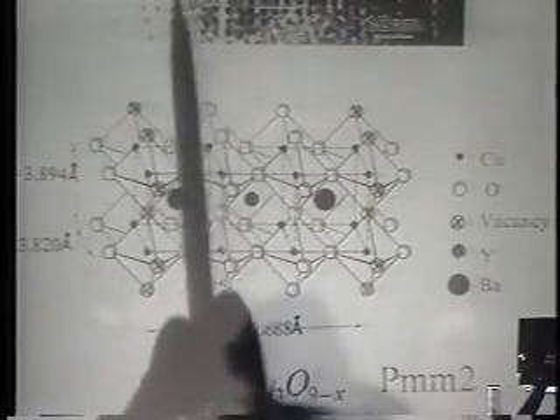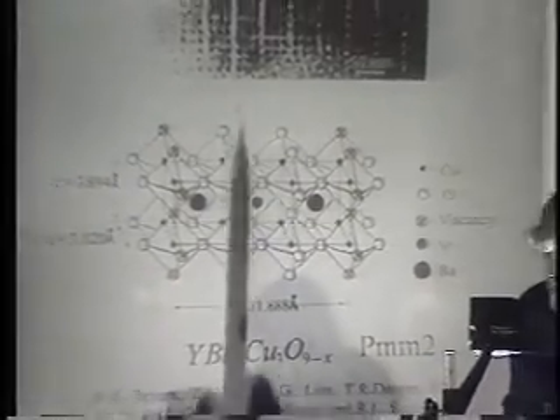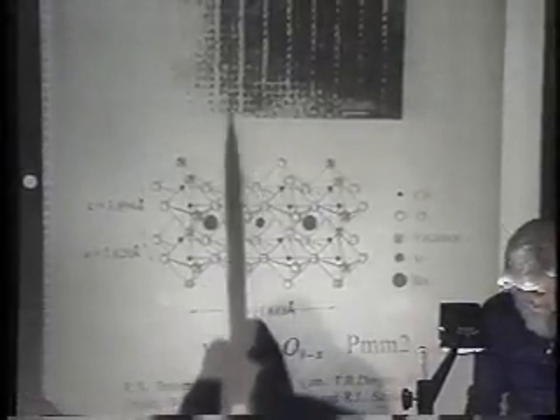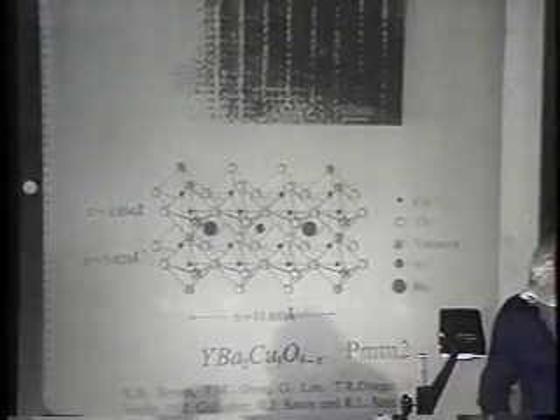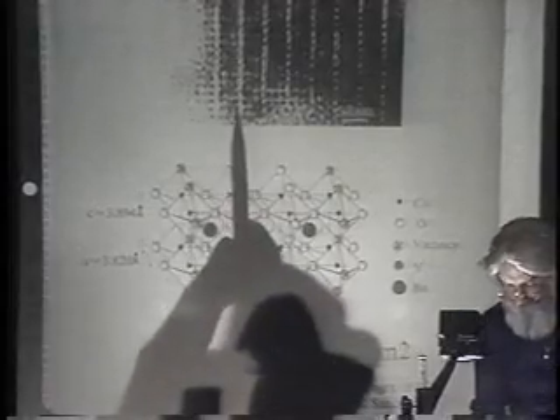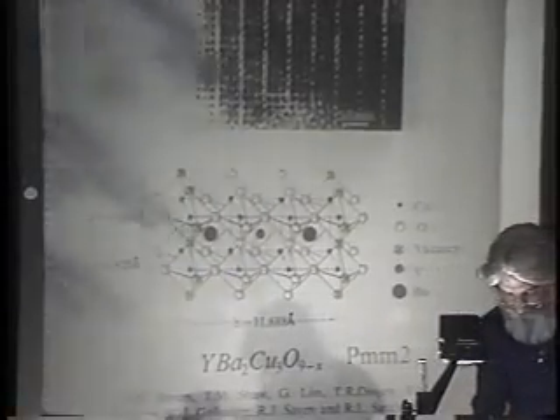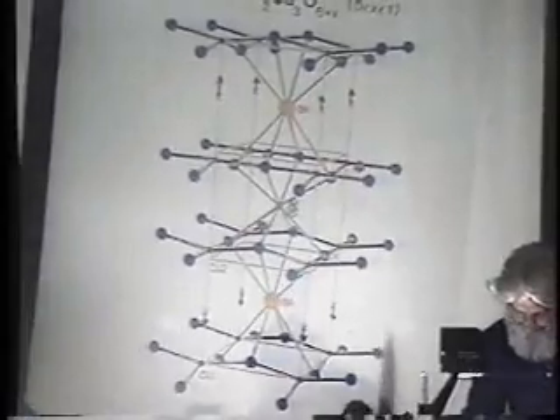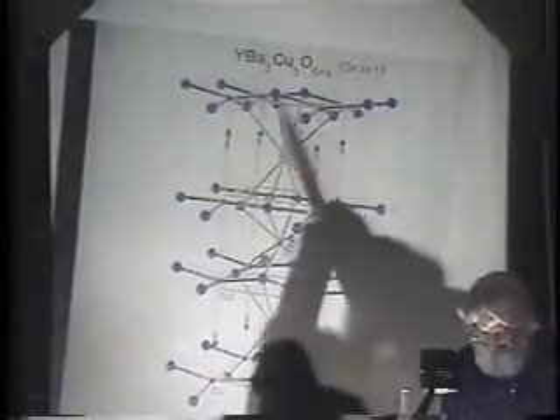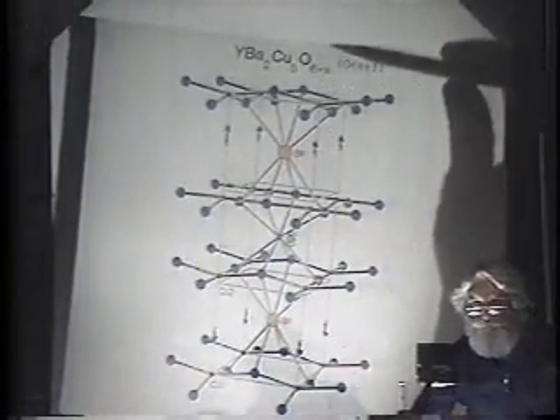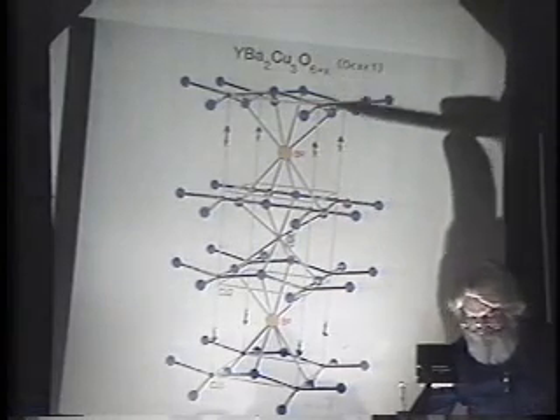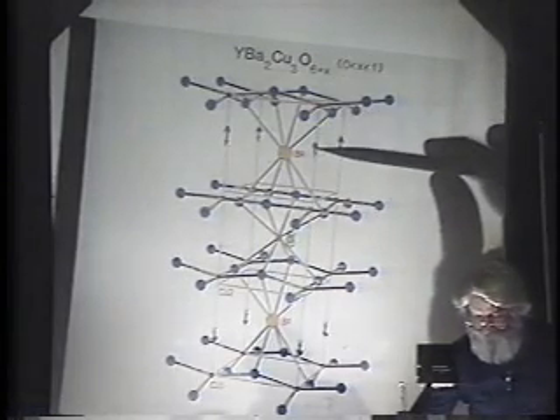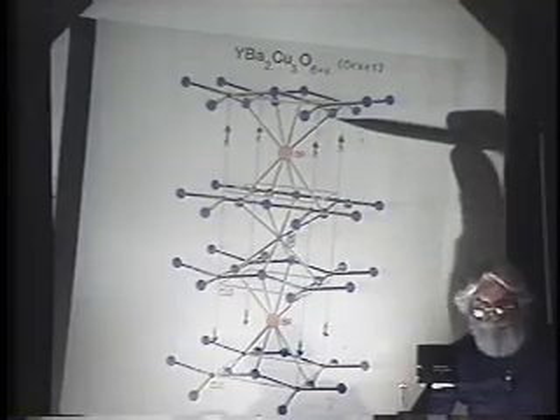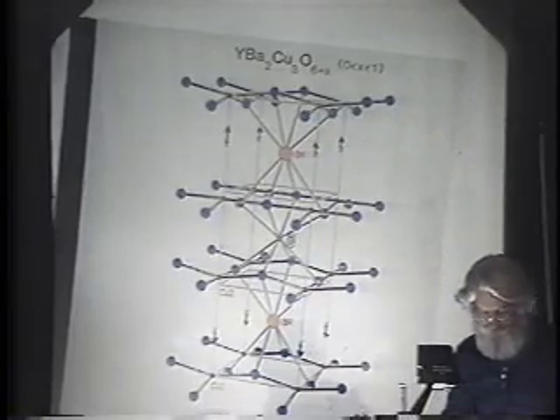Okay, what we now see from Bob Hazen's nice results is that this could possibly be a reconstruction going on in the copper basal plane, opening up these white spaces where the electron beam just pours right through, and that what we're seeing are the copper vacancies along this line, and then a spreading of the space between the barium atoms due to this reconstruction caused by oxygens in the barium plane moving toward the copper. And I think the story is beginning to look very, very pretty in that regard.